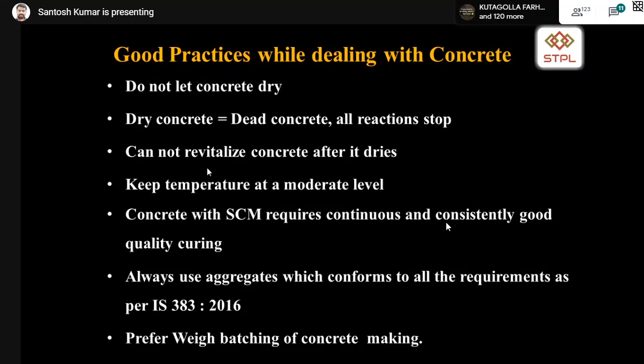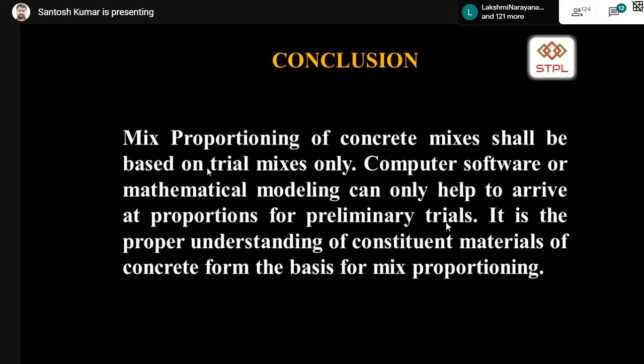and keep the temperature at a moderate level. Concrete with supplementary cementitious materials requires continuous and consistent good quality curing. As I told you, always use aggregates which conform to IS 383. Prefer weigh batching always. Don't prefer volume batching. And coming to the conclusion, mix proportions of concrete mixes shall be based on trial mixes only.